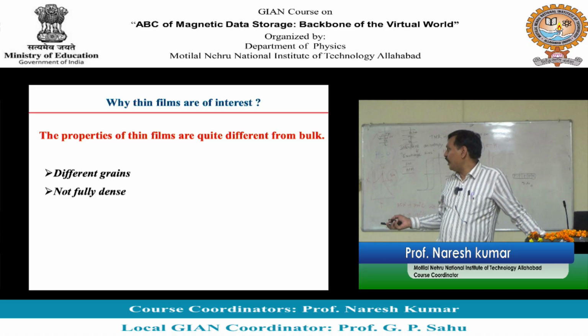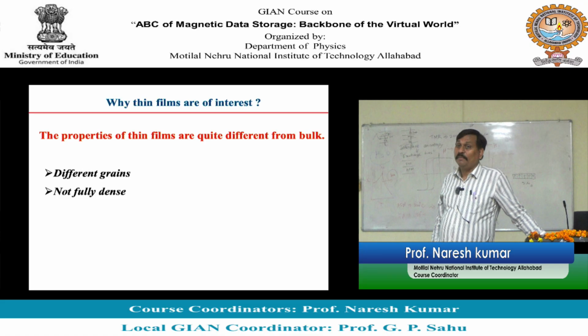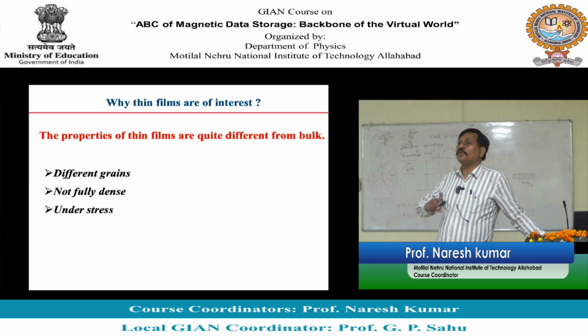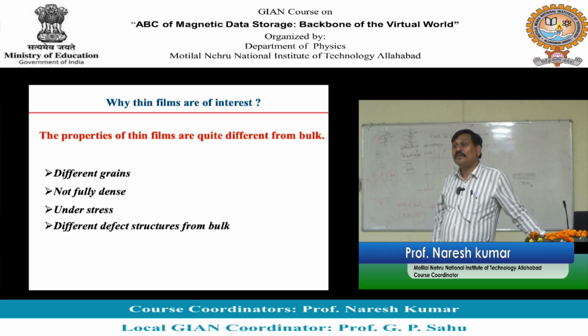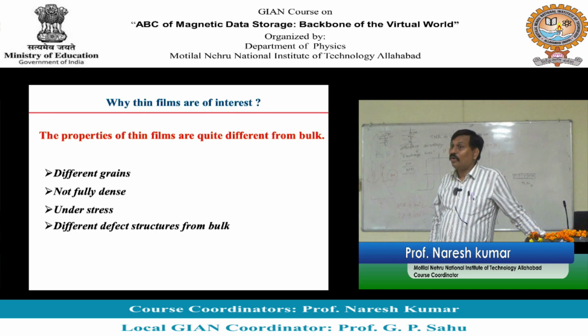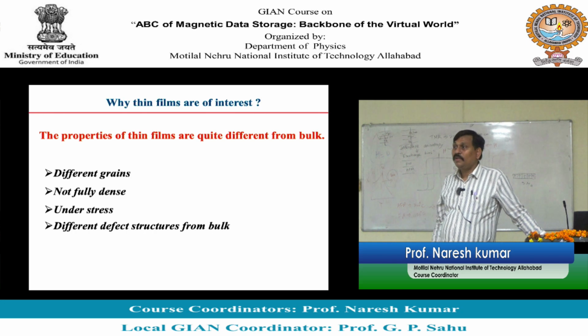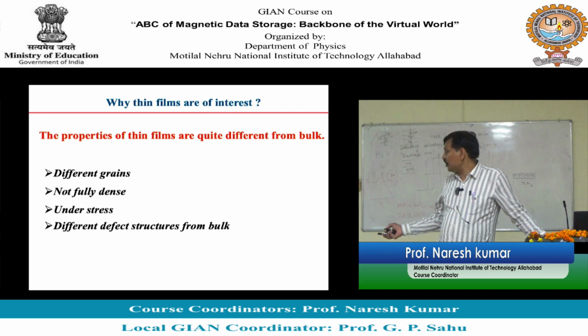Second, they are not fully dense, they might be porous. Since these films are deposited over a substrate, this may result in some kind of stress. They may have a totally different structure as compared to the bulk. If it is cubic in bulk, it may become orthorhombic in film, or tetragonal in film. So if there is a change in structure, it will result in a change in properties.